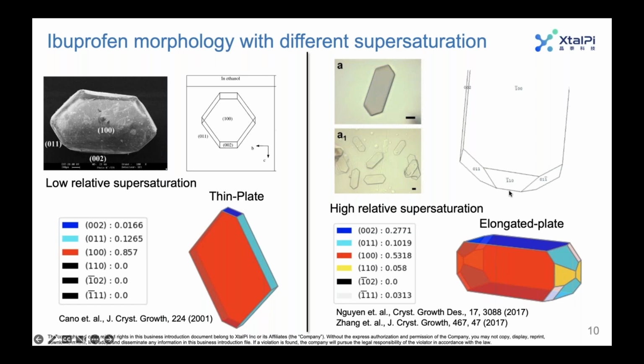We were able to simulate that by increasing the number of API molecules in the solution phase of the simulations. The combination of a tailor-made force field with molecular dynamics is able to capture that elongation of the 002 face and the appearance of some of those other morphological faces on the tip of this morphology.